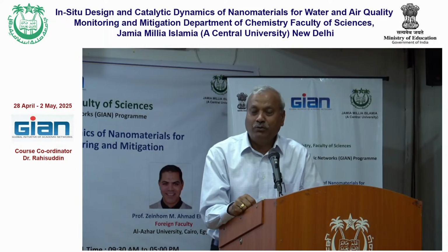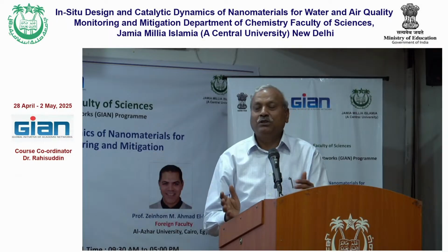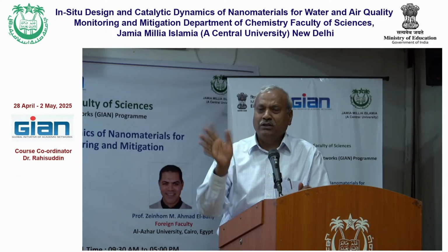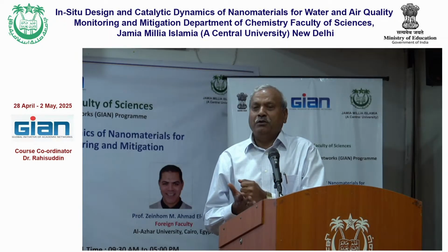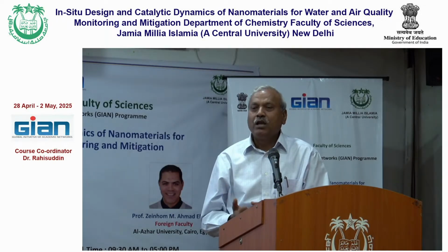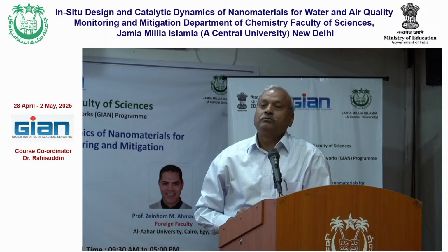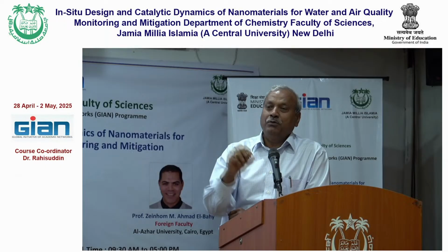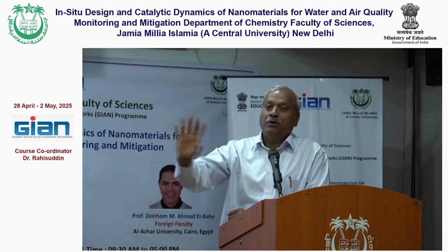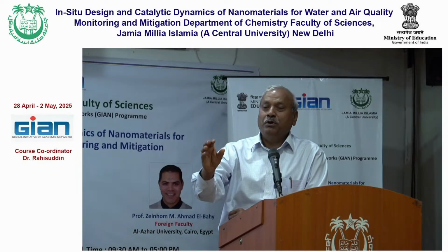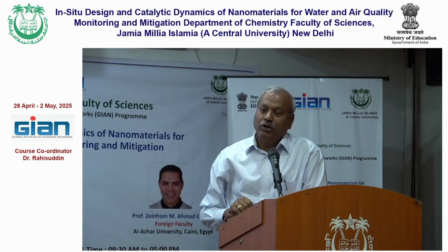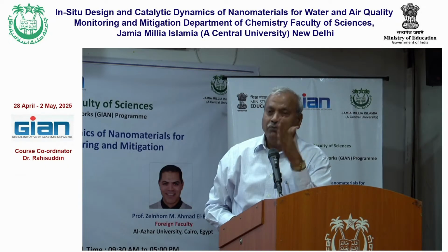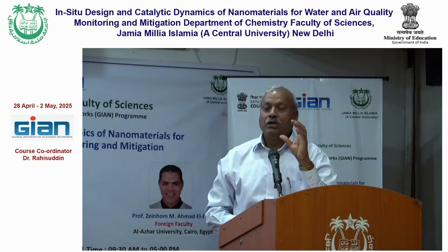Sometimes what we have observed, I'm not showing you here the homogeneous chemistry. In a homogeneous system, we had a vanadium 4 compound. In one case, not in all cases, we just simply ground it using a pestle mortar, and it oxidized to vanadium 5. While recording the magnetic property, we prepared it today, and after 1 week recorded the compound, the magnetic property became diamagnetic. The second day you prepare, half of that one electron is going down, oxidizing.